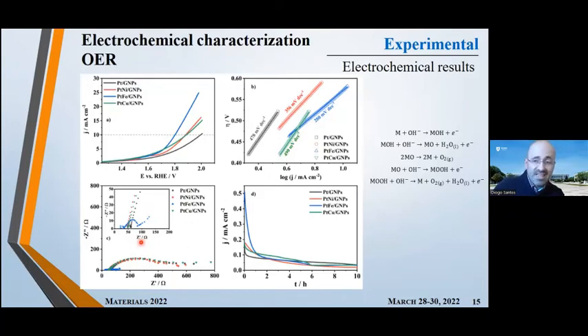As for the oxygen evolution reaction, we also ran these experiments. In this case, it's not the same approach. We don't study the effect of the rotation rate that is done in oxygen reduction reaction studies. For oxygen evolution, we scan the potential from open circuit potential until around 2 volts, and then based on these curves, we do Tafel analysis, which means a plot of the overpotential as a function of the log of current density, and from the slope of that plot, we get the Tafel slopes. Again, if we see here the lowest Tafel slope is for the platinum iron on the graphene nanoplatelets, which is a very good result.